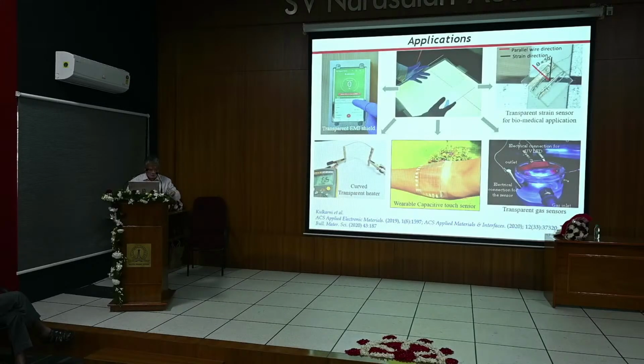Lots of applications. As you can see, this particular transparent EMI shield, this is the glass, cutout glass, fitted into a box like this. Inside you see a smartphone screen, which is showing number 0. Number 0 is actually how effectively the EMI is able to penetrate. 0 means it is not able to penetrate. So it means it's the EMI shield. It's a Faraday cage, just the difference is that it is transparent. Usually you have Faraday cages which are completely opaque, but here is a transparent one.